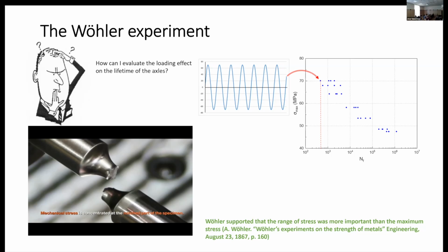We have to account for the experimental error because we always have experimental error. When we put the material on the machine, we might put it a bit misaligned, or in a different way. In testing of specimens like prismatic specimens, we might also change or affect the behavior by changing the pressure of the machine, the gripping pressure. So there are a lot of reasons for having this experimental scatter. It may have a notch or a stress concentration point, so it changes.